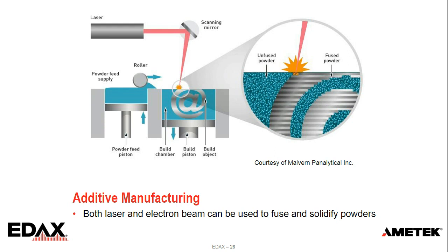This is just an example from Malvern Panalytical, where you have a bed of powdered material. We hit the powder, in this case with a laser, but both lasers and electron beams can be used. It fuses the powder particles together and solidifies them, so we can use the laser to raster out the area we're interested in. Once the layer is complete, we drop the build platform down, reset the powder on top, and do another layer. And so we can build complex shapes pretty easily with additive manufacturing.